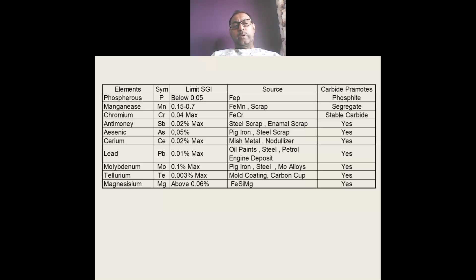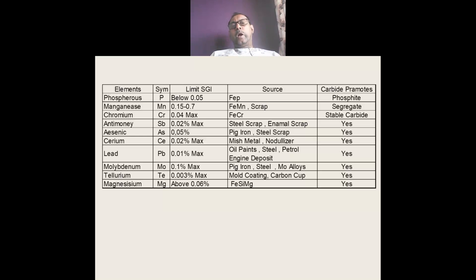Last but not least, magnesium can also promote carbide if it crosses the limit of 0.06% in ductile iron. Though magnesium is essential for the formation of nodularity in ductile iron, excess residual magnesium above 0.06% can promote carbides, thus hampering machinability and also giving rise to shrinkage tendency. So controlling these elements within their limits is essential to avoid poor machinability and to eliminate carbide formation.